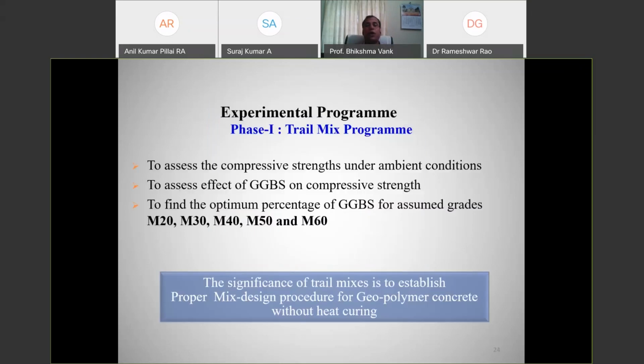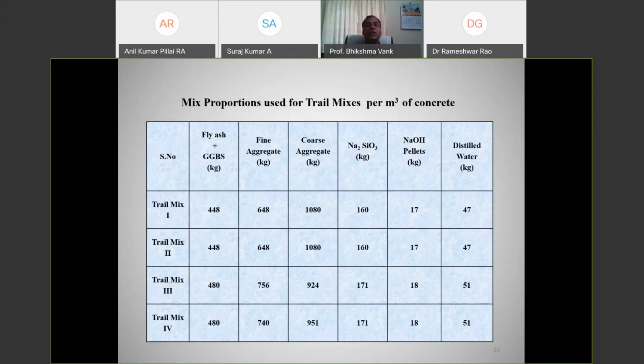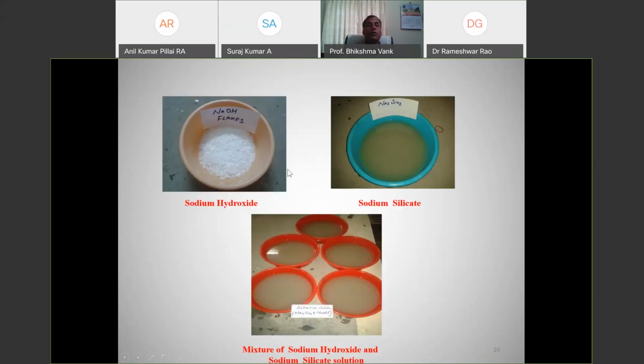Trial mix 1, several trials we have done. Phase 1 trial mix programs for M20 to M60. Each trial mix we have seen, per cubic meter of concrete: trial mix 1, trial mix 2, trial mix 3, trial mix 4 we have done, with fly ash plus GGBS, fine aggregate, coarse aggregate, sodium silicate, sodium hydroxide, everything. And this is how sodium hydroxide and sodium silicate look. This is how it is prepared actually, a mixture of sodium hydroxide and sodium silicate.